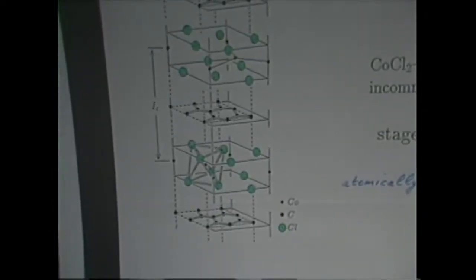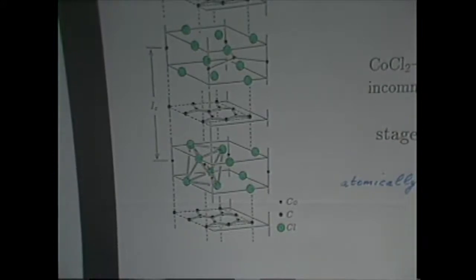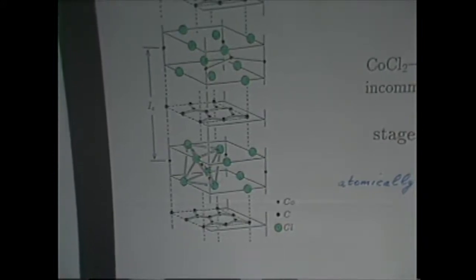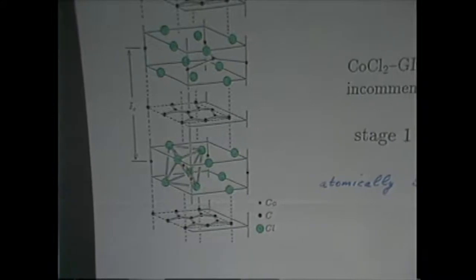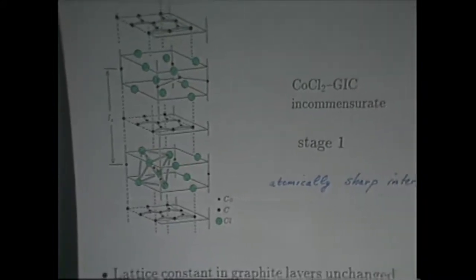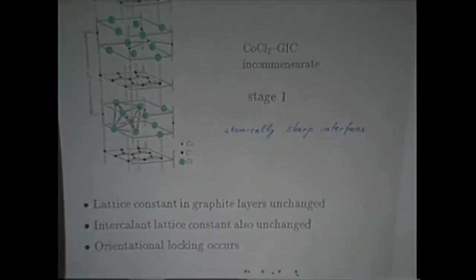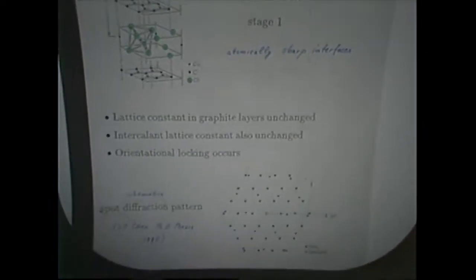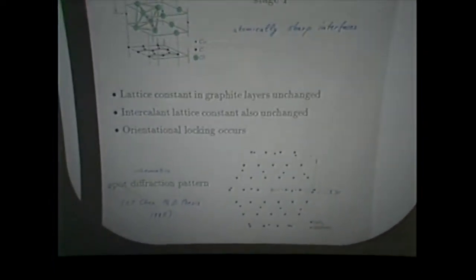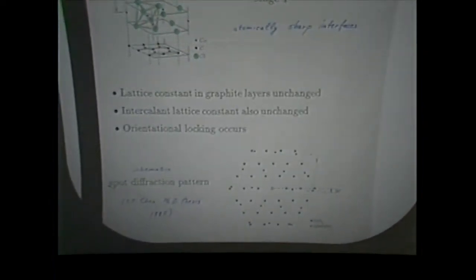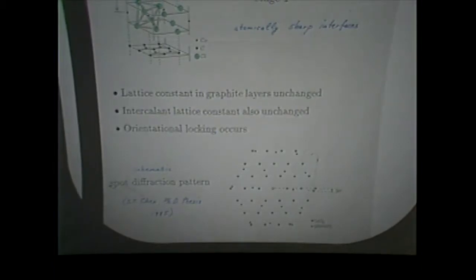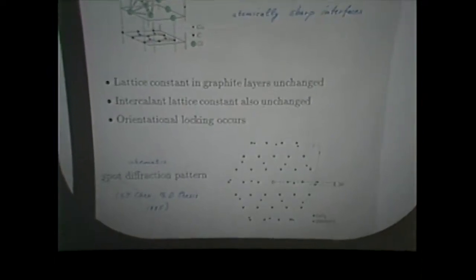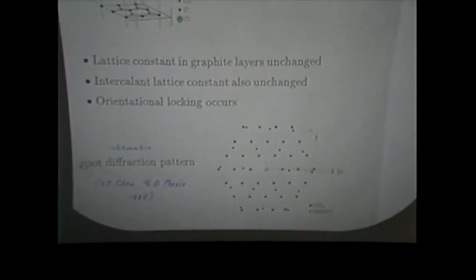But there are several differences between this and what happens in molecular beam epitaxy. For one thing, there's an orientational locking of the intercalant with respect to the graphite. That is, the intercalant doesn't go in any which way, but it has some preferred directions where it can stay away from the graphite layer in a maximal sense. The other thing that happens that's different from molecular beam epitaxy is you have atomically sharp interfaces.